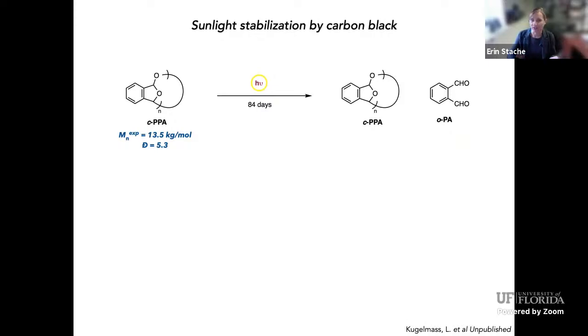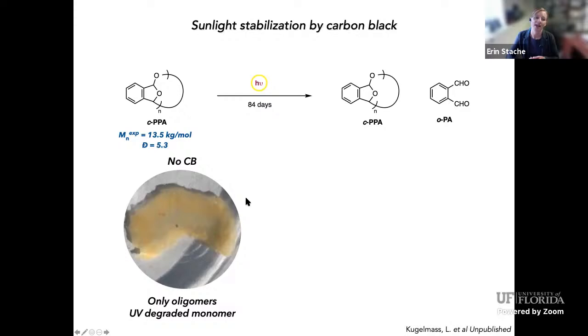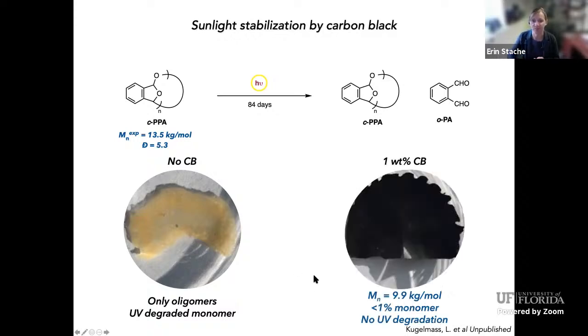What's actually still in the film? This is the polymer that she used to make the film, and with the absence of carbon black, all we see are oligomers. There's nothing in the GPC trace, and in the NMR, it's mostly degraded monomer. So it's not even phthalate anymore. We can't recover it. So this polymer is not stable to sunlight. It's really not stable to ambient light for a long period of time.